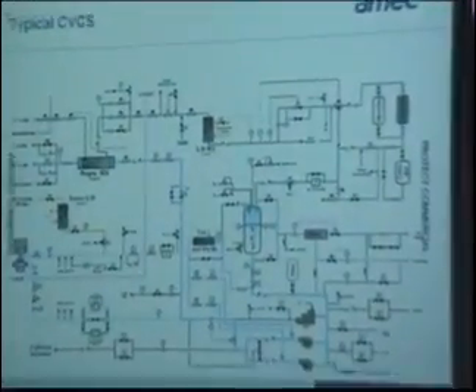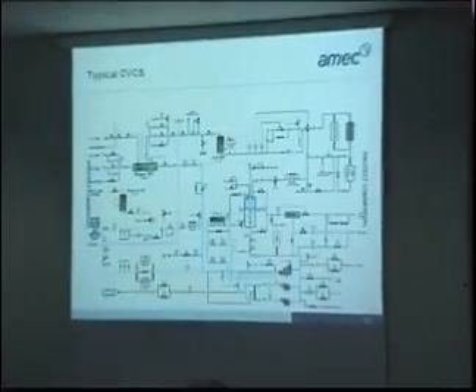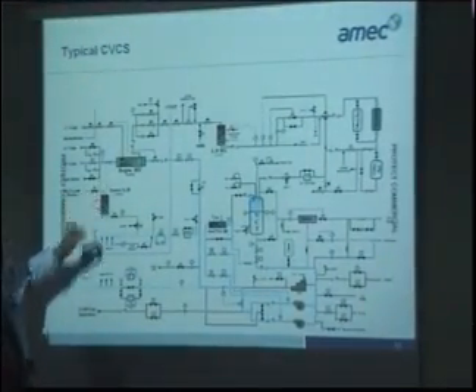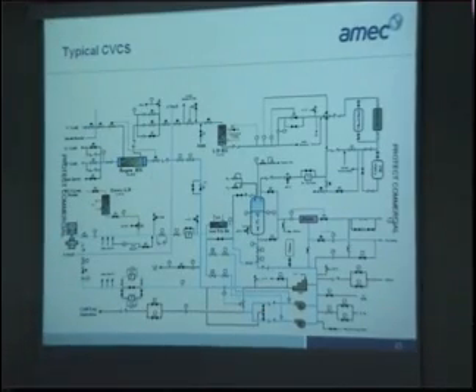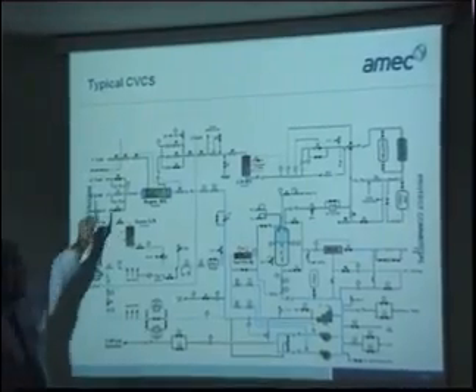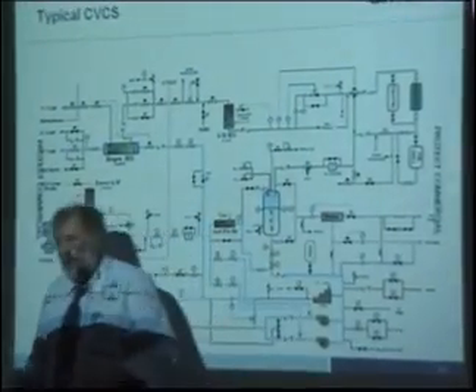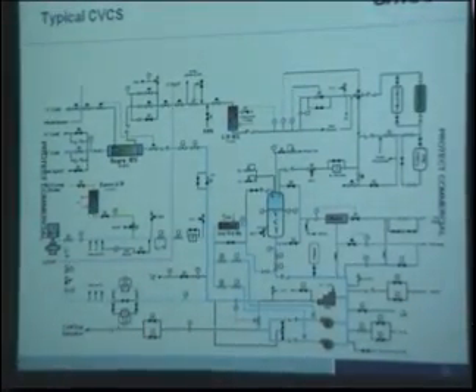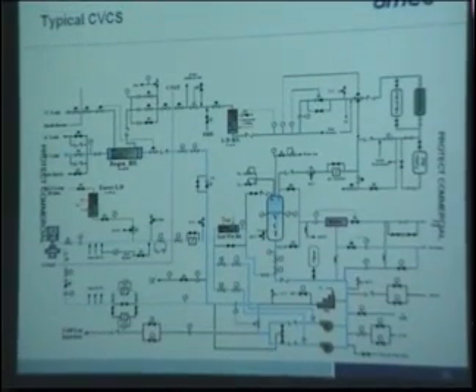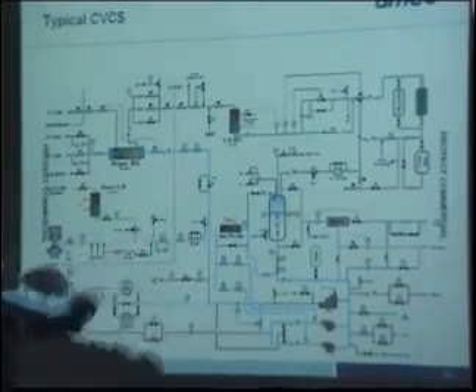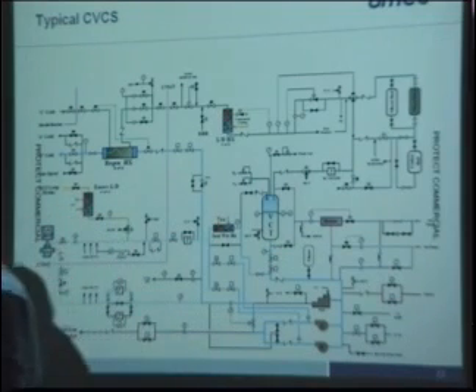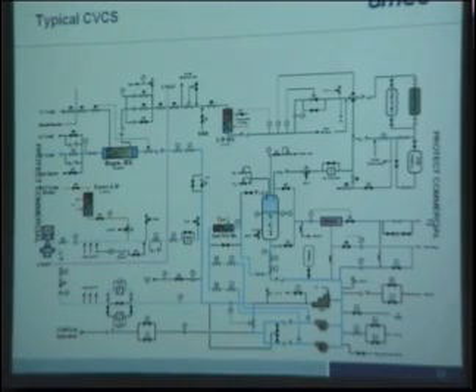And again, sorry for the complication about this. Basically, you've got a heat exchanger. This operates at about 45 centigrade, so it's near ambient temperature. So you have a heat exchanger to bring it down. You've got some ion exchange resins here. These control taking out the soluble crud, the ions, cobalts, any fission products. You've got a mixed bed there, things like iodine, and you've got a cation bed. Now the cation bed is purely there to control the lithium. You're producing lithium from the B10 n-alpha reaction all the time. It has to be taken out on the cation bed.